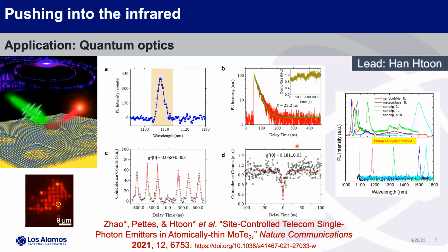So what we did was we got a material with a smaller band gap. It's a little less stable. And this is molybdenum telluride. And one of our postdocs made little polymer pillars. It's not hard to make. They're maybe 200 nanometers diameter, 50 nanometers in height. And then he put molybdenum telluride on it. So nothing new by any stretch of the imagination. It's just the material was new. It's not super stable. It's hard to work with. But he was able to put it on very quickly.